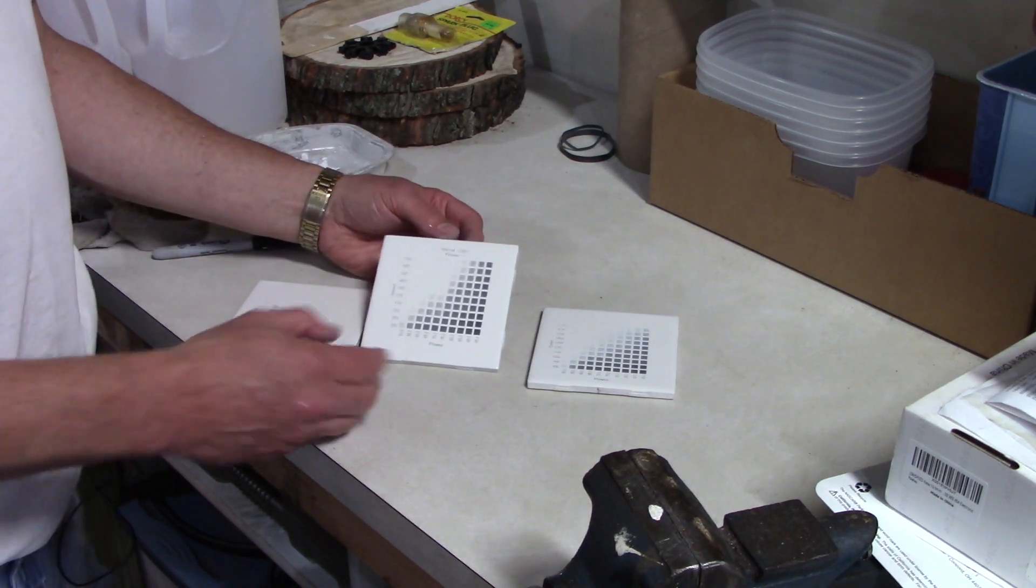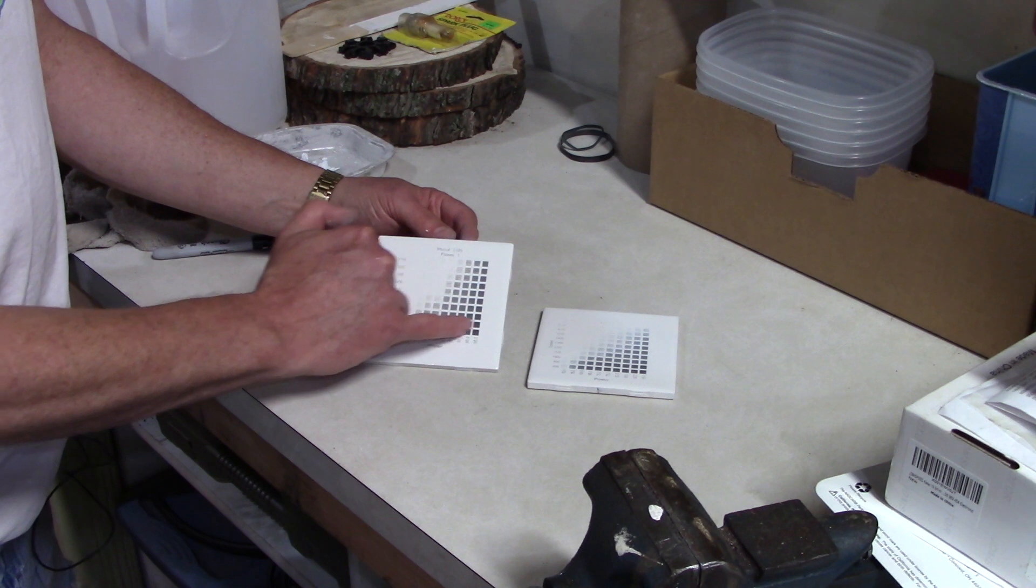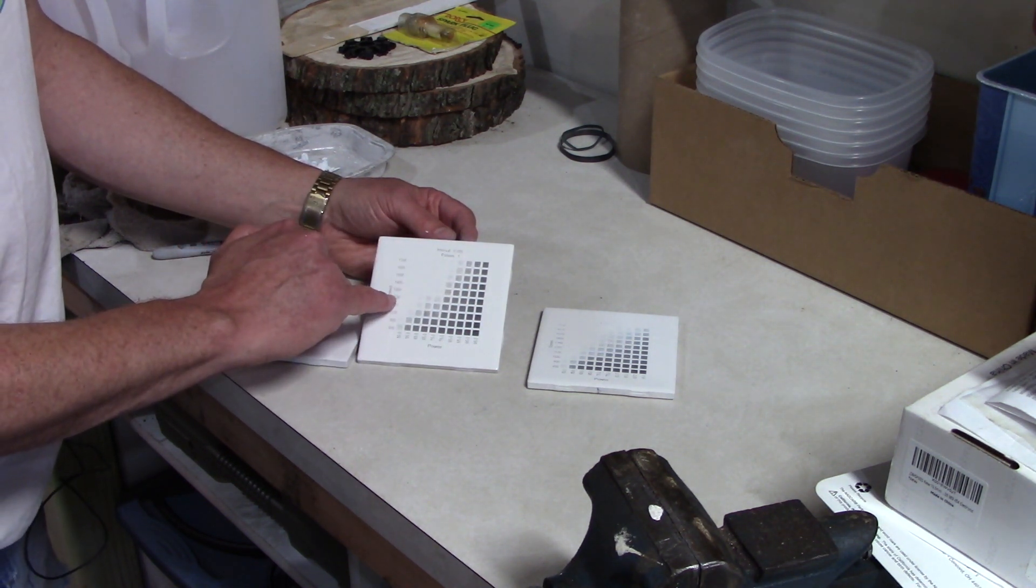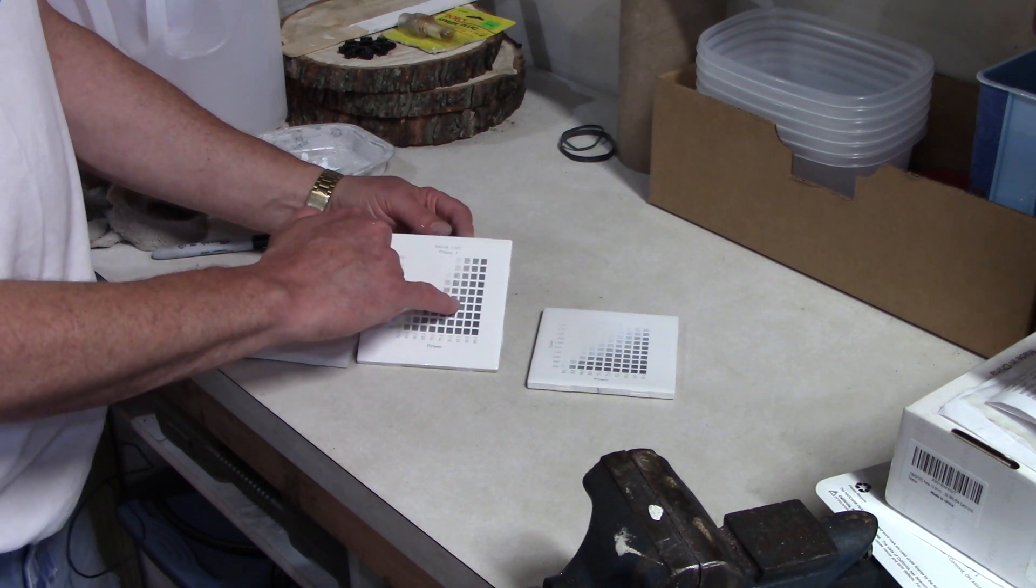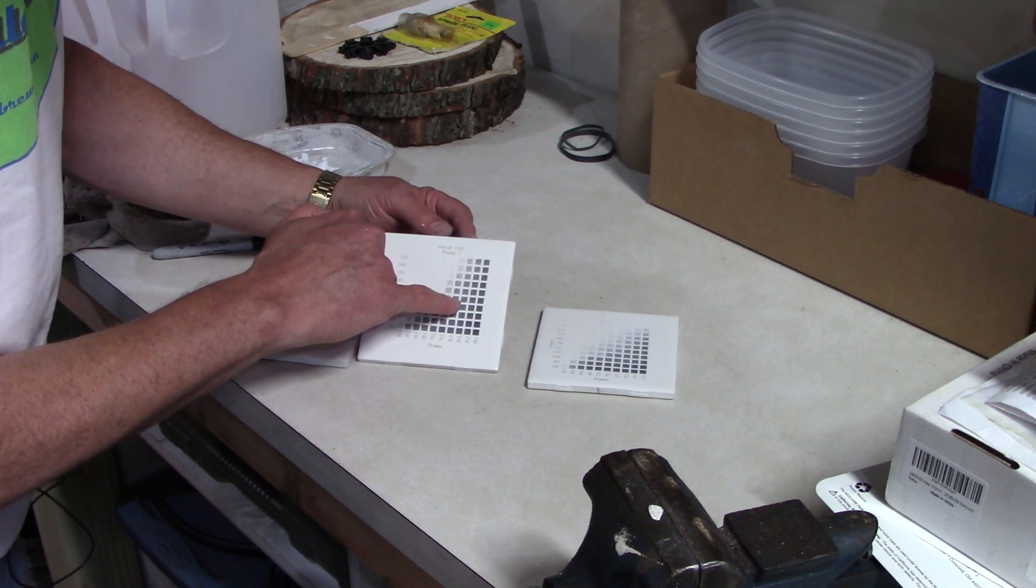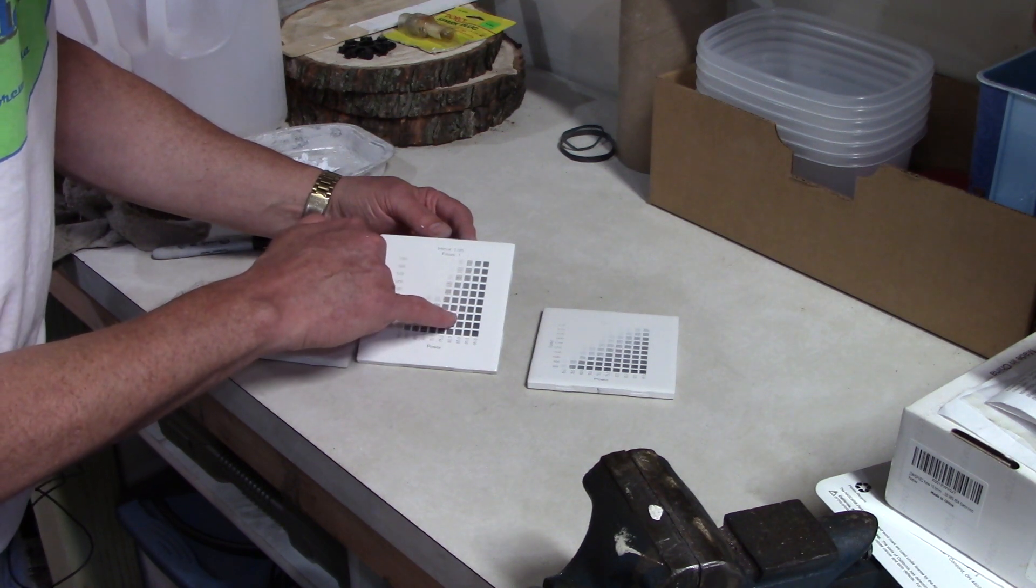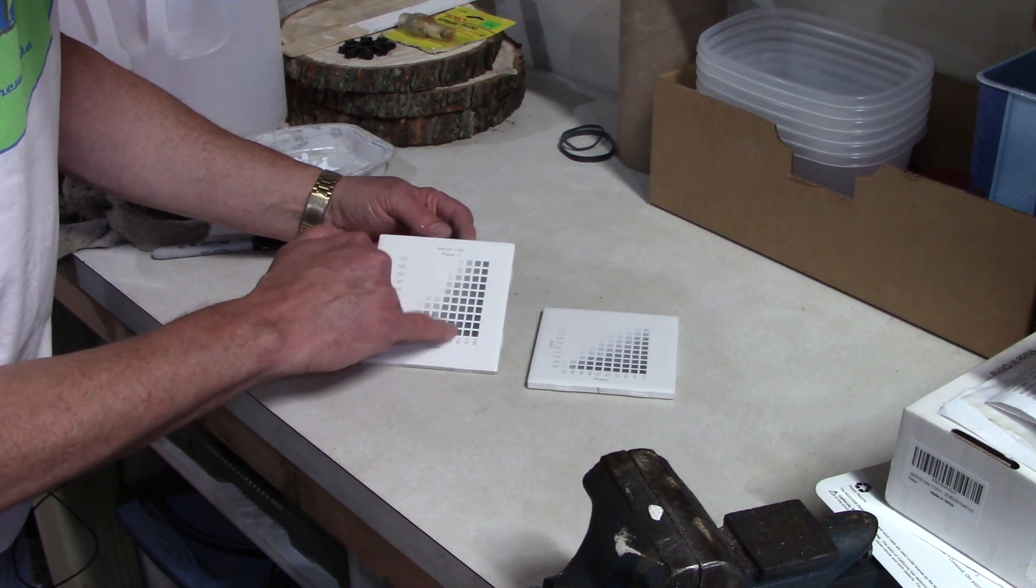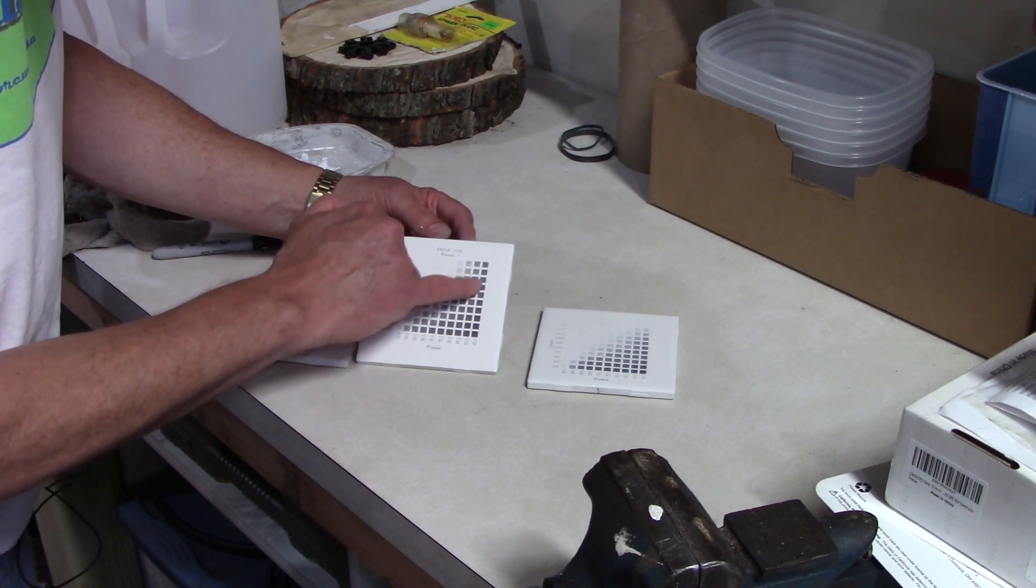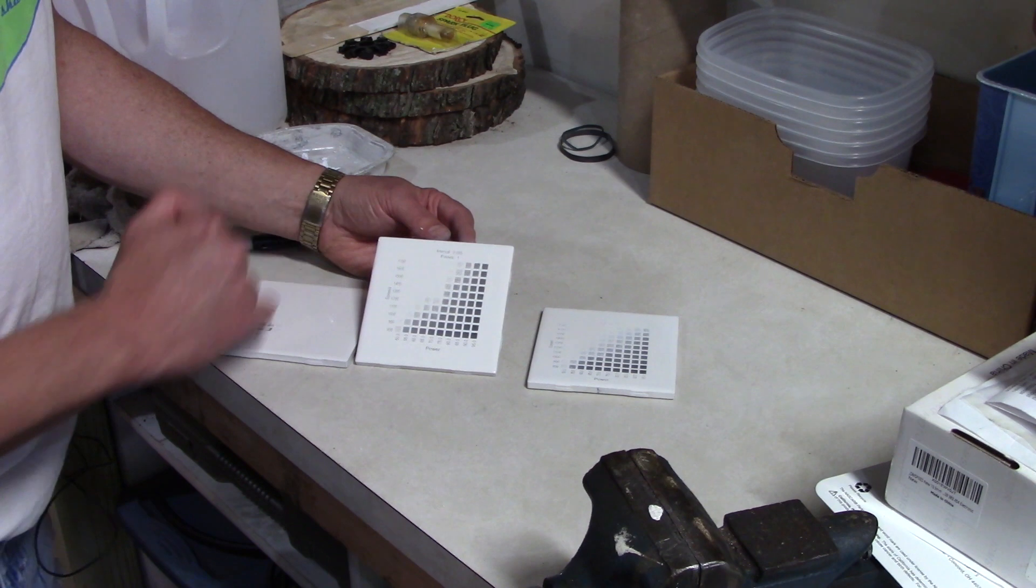This next one was two light coats. So light coat horizontally, one vertically. And we ended up with some pretty good stuff down in here. Again, our normal speed is 12 at 85. So that puts us on this one. Looks like either the parameter needs to change a little bit, maybe slow it down to 1100, go 90 percent. Or we want to stay at 85 percent, we come down to 1000. But these are really good down here. They're nice and dark. And then of course, these are lighter and lighter. And then you really can't see the stuff up here.